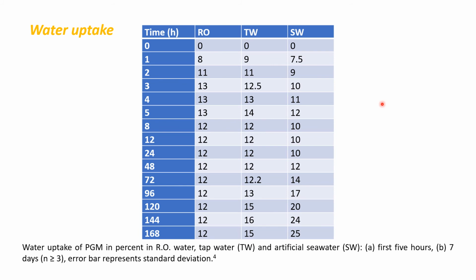Here are the water uptake test results for PGM film derived from unmodified PGM prepolymer. Water uptake is slightly higher in tap water than in seawater environments. Water uptake in seawater eventually reaches around 25%, much higher than in RO and TW. These results indicate that the presence of salt appears to have slowed the water molecules entering the prepolymer film initially, but eventually increased the water absorption ratio of the polymer over longer periods. Since PGM is a network polymer with hydroxyl groups throughout, it is likely that with the inclusion of metal cations, more water molecules are transported into the bulk polymer, leading to higher water absorption.